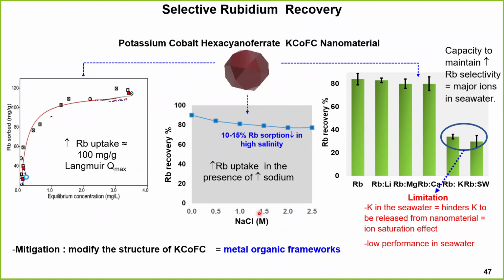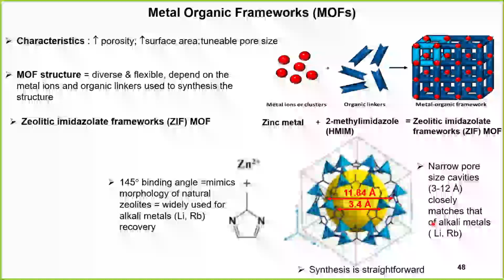Then when you increase your sodium concentration, your rubidium recovery decreases a little bit, around 10 to 15%, but it's still a manageable level. We compared the recovery with lithium, rubidium, rubidium magnesium, rubidium potassium, and rubidium seawater. So when you have a replacement with rubidium in KCoFC, the recovery is relatively low, and after regeneration we also have to effectively remove this potassium. So potassium and rubidium separation will be one of the challenges to utilize this process.